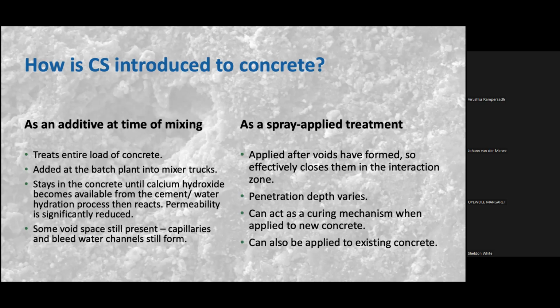You have two ways that it can be used. It can be used at time of placement, or about the time you can walk on the concrete, about the time without leaving an impression. That's where you get the most benefit, because you're closing up that void space early and holding evaporable water in the concrete. That means that it can be used as a curing mechanism when applied to new concrete. Because it's naturally forming these reaction products that hold that moisture in, when you use compressive strength development and drying shrinkage as your metrics for curing, it will beat even moist curing for 28 days. No one moist cures concrete for 28 days that I'm aware of. Rarely do you see moist curing done for more than 7 days. It can, however, also be applied to existing concrete.